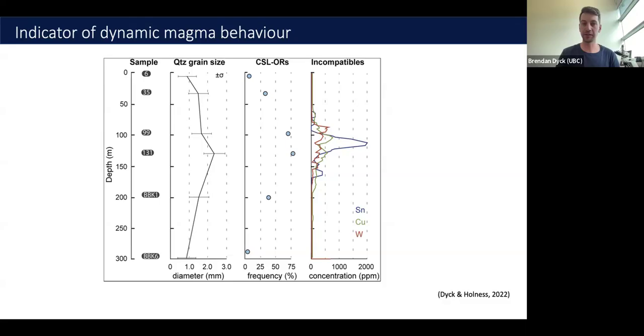Now, the implication of this, if we look at this particular sample I looked at, happens to be a historical and high-producing tin mine, so it's a cassiterite ore deposit. And if we look at the distribution of the mineral incompatible elements, things like tin, copper, and tungsten, that increases in towards a more central horizon. Similarly, the quartz grain size slightly increases in towards the center horizon. And what's really interesting is that the frequency of these low energy orientation relationships of our quartz clusters greatly increases in towards the center of our body.